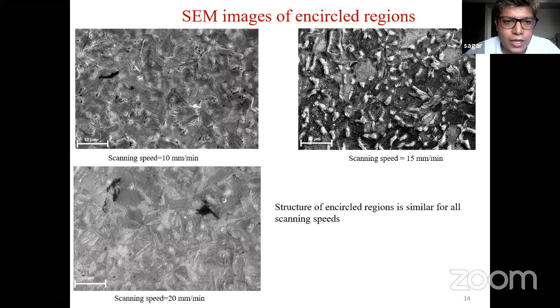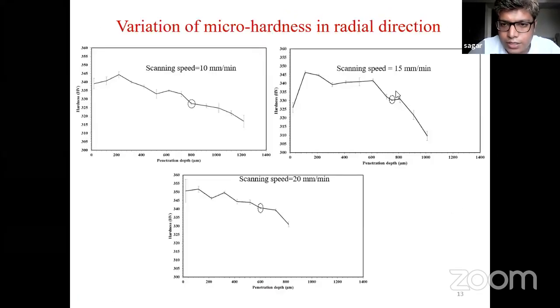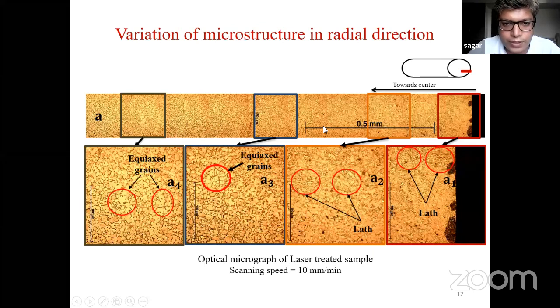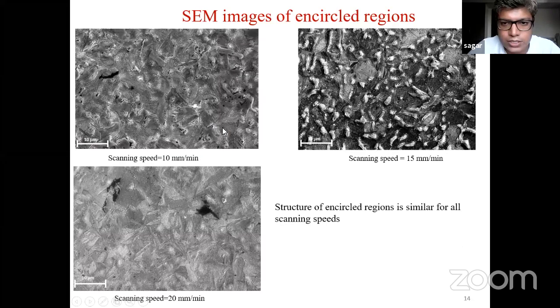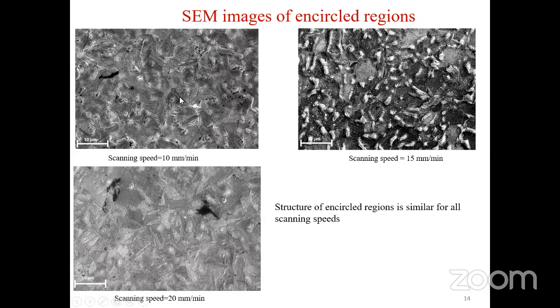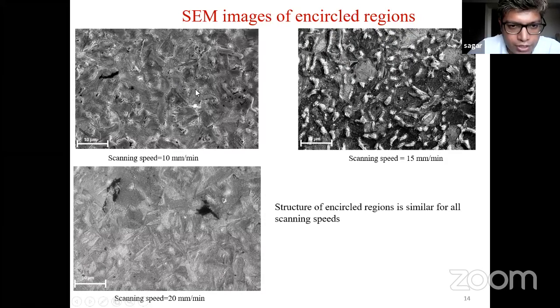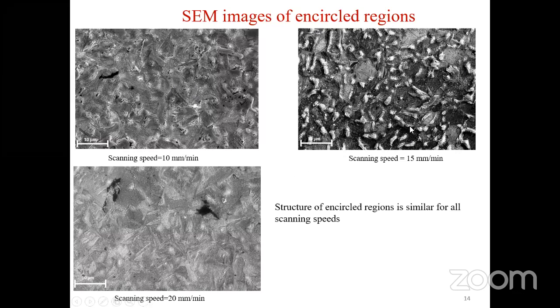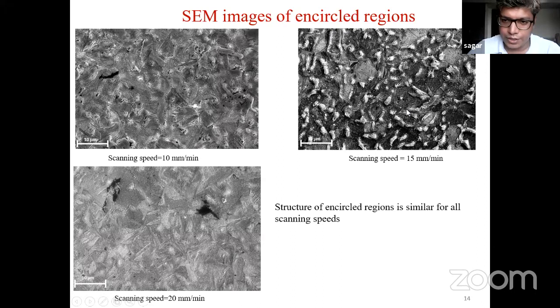Okay, so these are the micrographs. Here you could see the encircled region, and this encircled region is nothing but the penetration depth of the laser that we have calculated through optical measurements. At that encircled region, what is the microstructure? The microstructure is like this. These are the SEM images, scanning electron microscope images. Here you could see these are the grains and these are the grain boundaries. These boundaries everywhere have been affected due to the laser treatment.